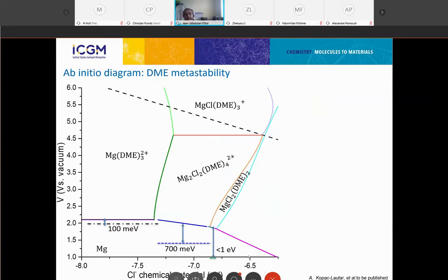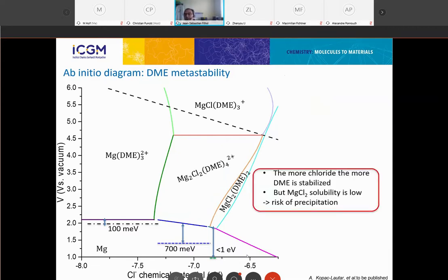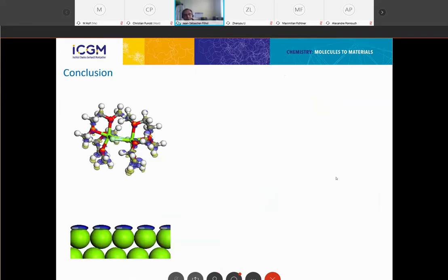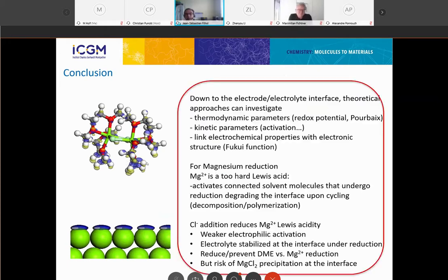So chloride is certainly a very good thing to improve the electrolyte stability by, in fact, decreasing the electrophilicity of magnesium. But of course, if you add too much chloride, you are going to precipitate MgCl2 and you are going to clog your electrode. So to conclude, here is just the explanation that is Mg2Cl2. And when you look at Mg2Cl2, you don't see any reduction of the DME molecules. So it's really the proof that the chloride has a protective behavior with this kind of system.